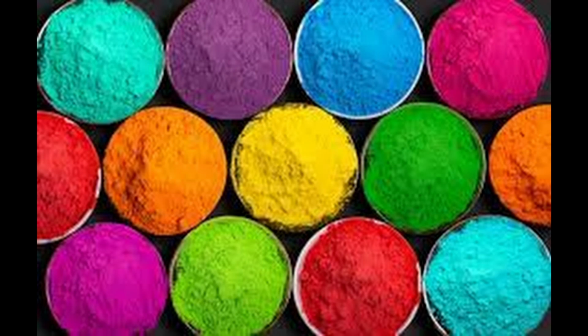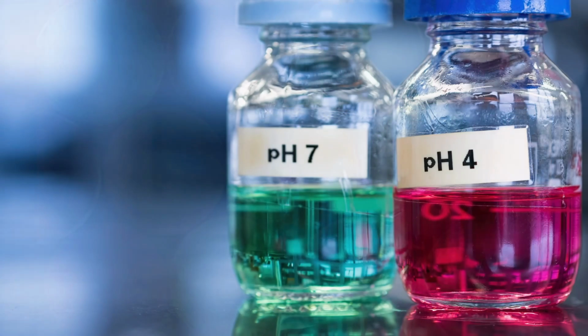The next thing we potentially have to deal with comes from our pigments. With water in the mix, some of our pigments may dissolve and change the chemistry of the overall mixture, making it too acid or alkaline, for example. Other pigments may only be soluble or the correct colour at certain specific levels of acid, base or neutrality. To stabilise all of this, we may add a buffer compound, which effectively absorbs small changes in the local environment to keep things at a certain specific range.